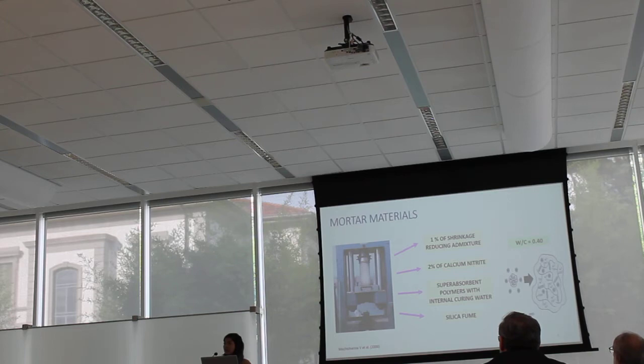So if you are going to use all these admixtures, you have to choose a good model to design your mortars. In this case, we chose the Powers model with the modification of Professor Jensen, who changed the Powers model to use cement and silica fume in the system.